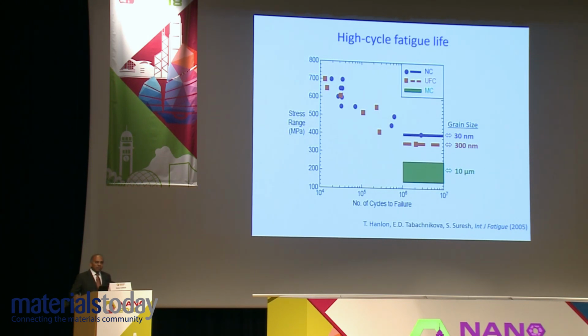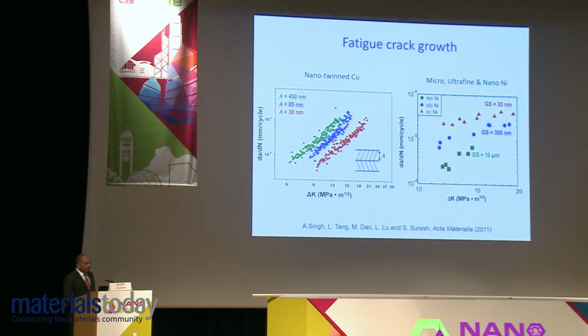But then, if it's strain control fatigue, you will see that there is almost no data in the literature. There is very little data because specimens aren't large enough to do a valid cyclic deformation test by controlling strains. So when you go to low cycle fatigue, you run into the problem that the beneficial effects of grain refinement begin to disappear. And the same thing happens if you look at nanostructured materials, on your right-hand side, which shows data in nanocrystalline nickel, ultra-fine grain nickel, and microcrystalline nickel.